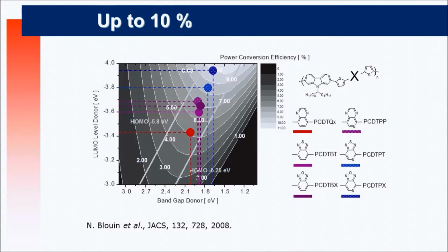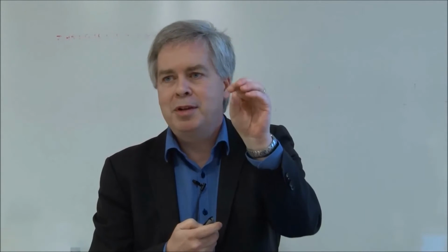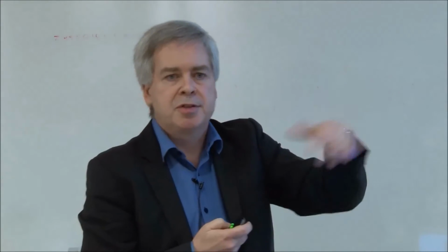So if everything is perfect, you may expect something about 10% here with this polymer, and about 7% with this polymer here. And clearly, if you put a pyridine core here, you should get better efficiencies compared to what I call the benzene ring, or benzene-like ring comonomers. And you won't be surprised, those polymers work quite well, and it was a disaster with those ones. And clearly it's because for some reason, we have some acidic compounds in the device, and the pyridine were protonated. So the fact we have pyridine units became protonated with PEDOT:PSS, for instance, and that killed the device.